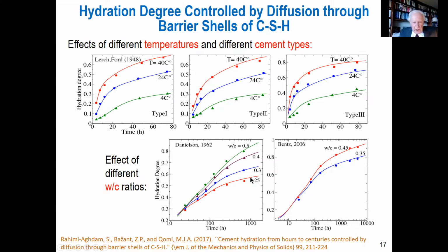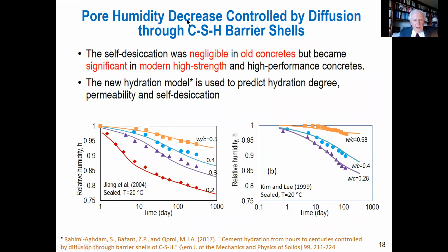As the water cement ratio goes down, it goes much slower because humidity decreases more rapidly. And these data are followed well. I fitted as well as Garboczi and Bentz's model from National Bureau of Standards. All right, so pore humidity decreases, controlled by diffusion through the CSH barrier shells. So this process, its rate is not determined by the chemical reaction actually, which is immediate, but it's totally controlled by diffusion through the barrier shells. Now the result is that water is withdrawn from pores, so there is self-desiccation.